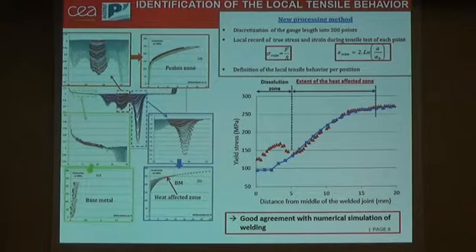From the result of this unique tensile test across the welding joints, and without being obliged to make different tests on micro-flat specimens, for example, we propose to use the results to identify the local tensile behavior along the welded joints through a new processing method that was developed. The method consists of discretizing the gauge length into 200 points and recording the true stress and strain during tensile tests, so that the local tensile behavior can be constructed at each position of the welded joints.